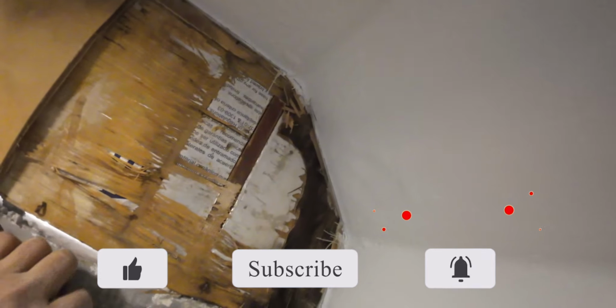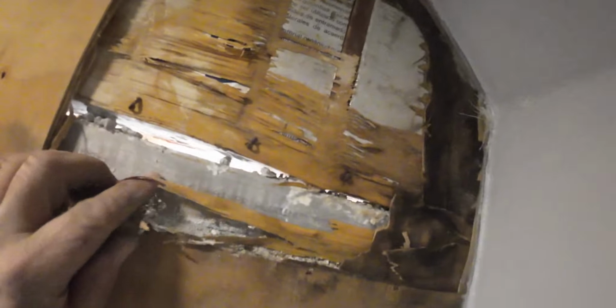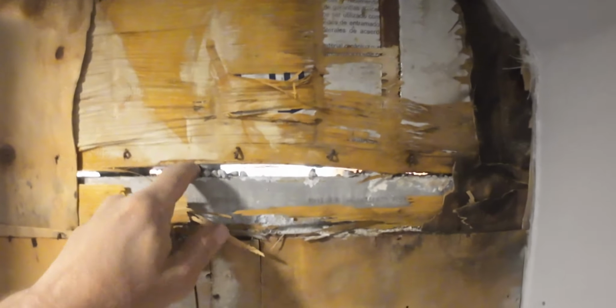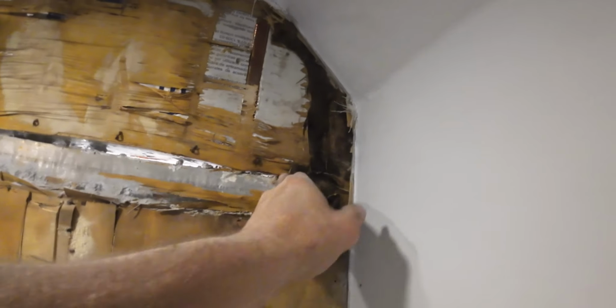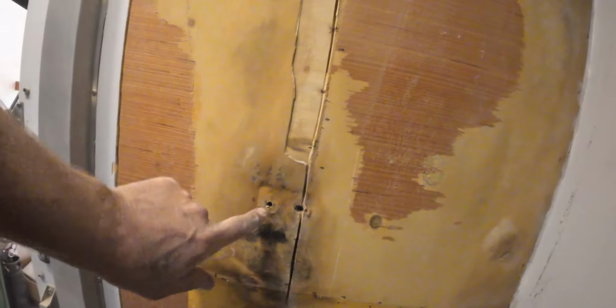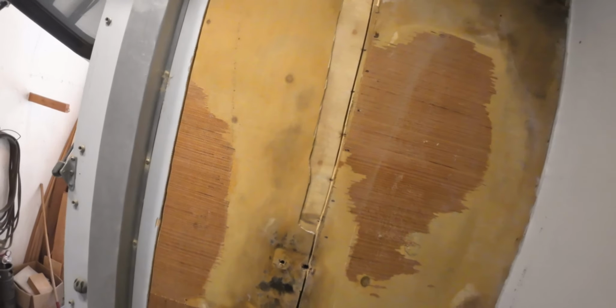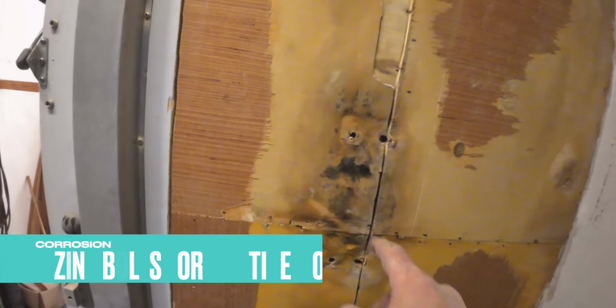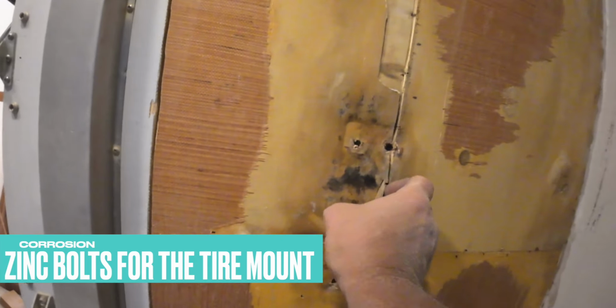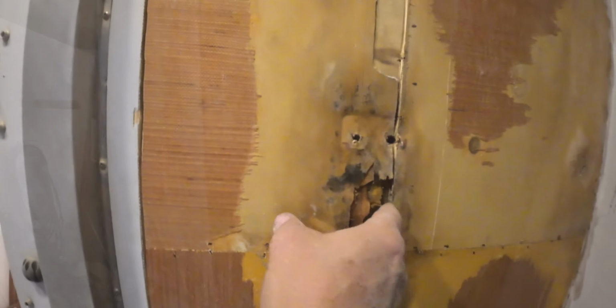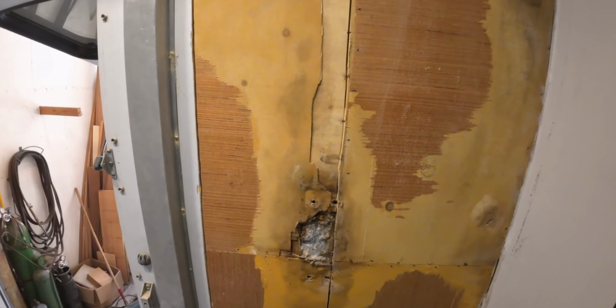So there's good and bad news. Water came in right here from the outside. The tube, look at all that white powder. That aluminum oxide swelled up and pushed that piece of wood up there. So what I think happened here is it got down in here. It loosened this wood here, but not very much, just over here in the corner where it first came in. Right around where the penetrations were for the spare tire is where it really developed a cancer. And I'm questioning whether or not this was a reaction with the zinc plated bolts and the aluminum together. But this is swollen pretty well. We'll pull it apart and let it dry out and go back and fix it.